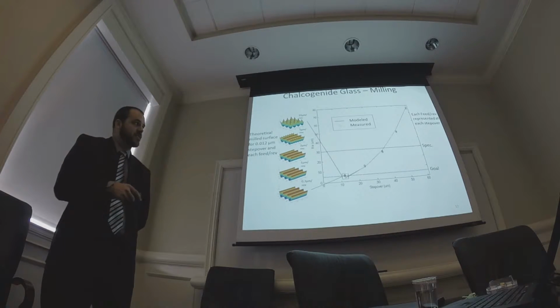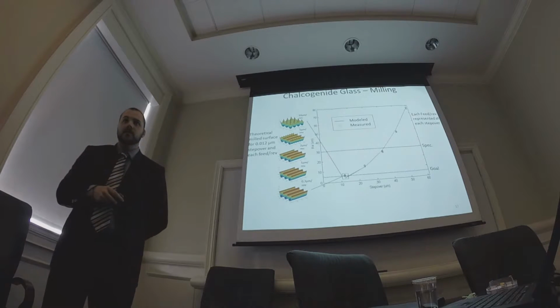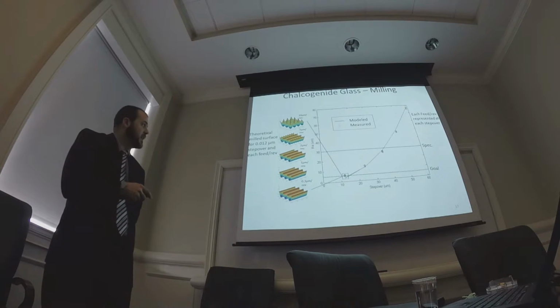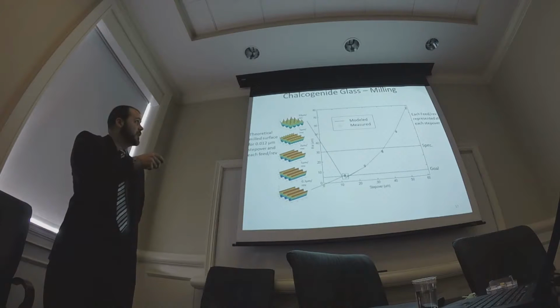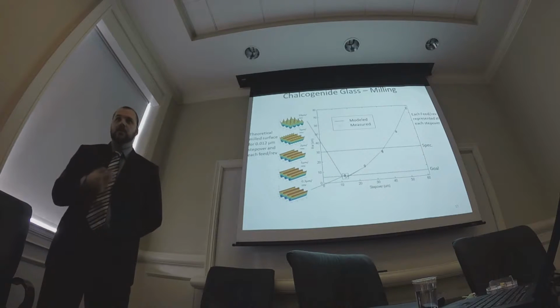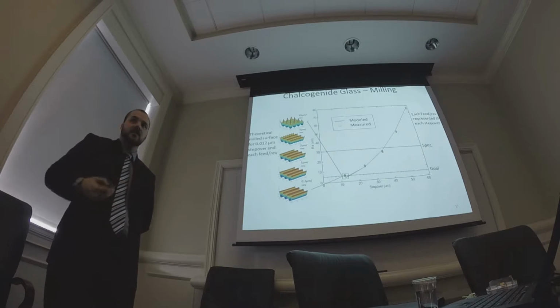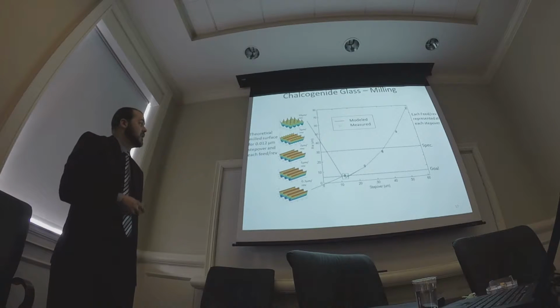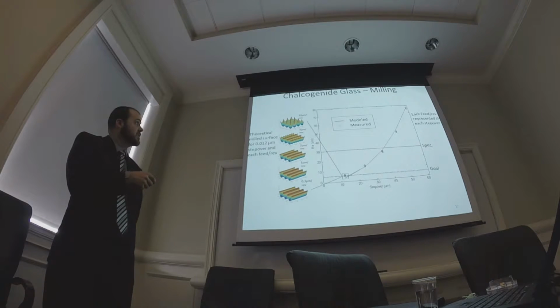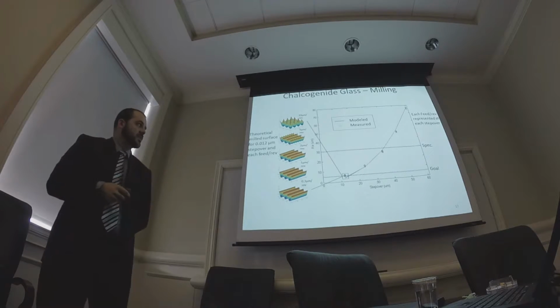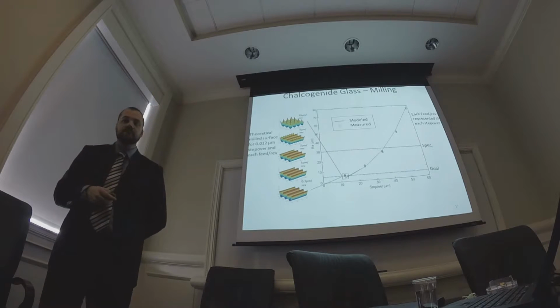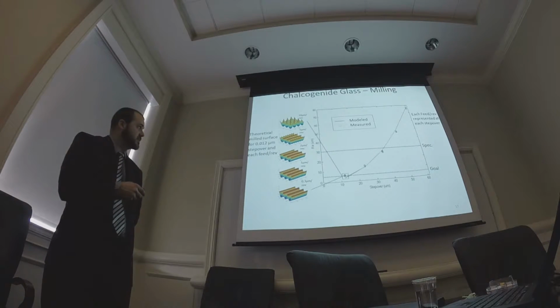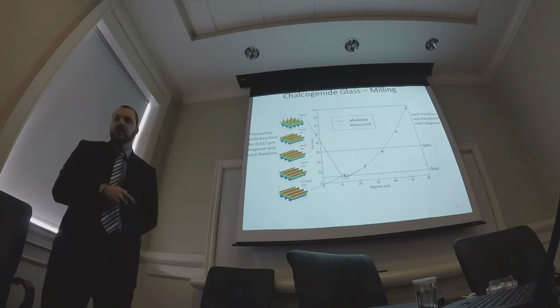These are the different feed per revs for the step over, for that one step over. And this is the theoretical shape we would see for a perfect tool, a perfect machine, synchronized chips as we moved along. The standard deviation of these surfaces is within a few percent of each other. These are all the same Y or Z scale.